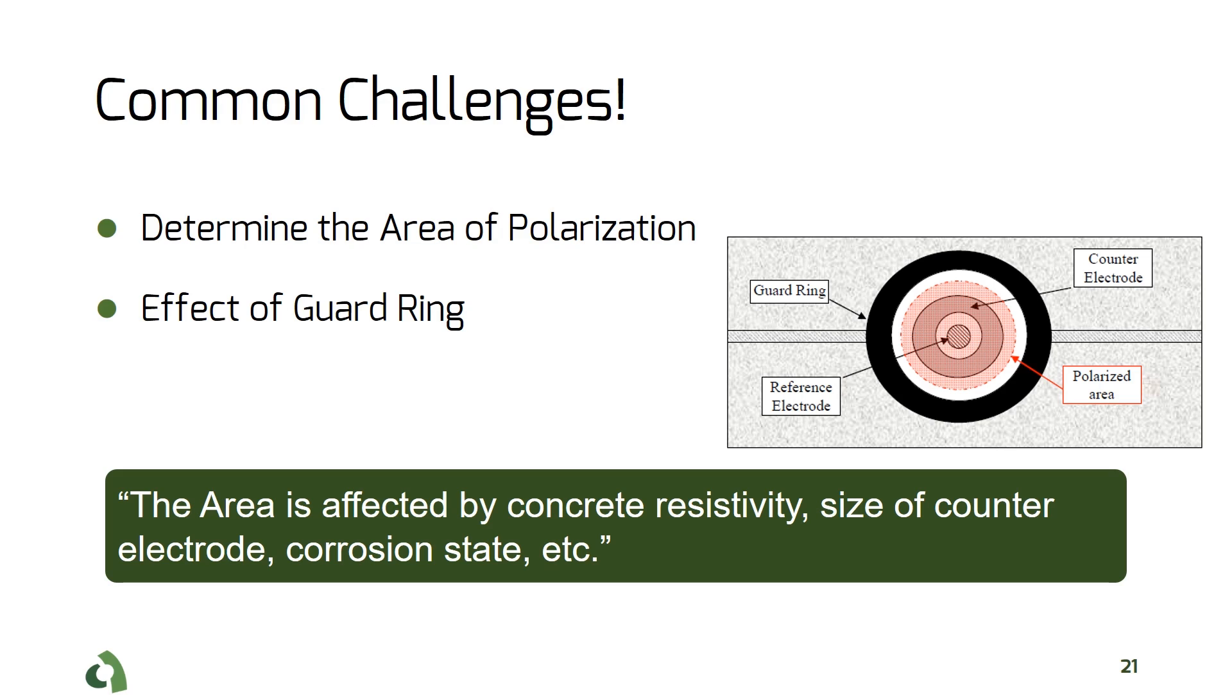A guard ring is usually used in this type of instrument to confine the current distribution along the rebar. Increasing cover thickness increases the polarized length, because the current signal distributes over a large part of the rebar.